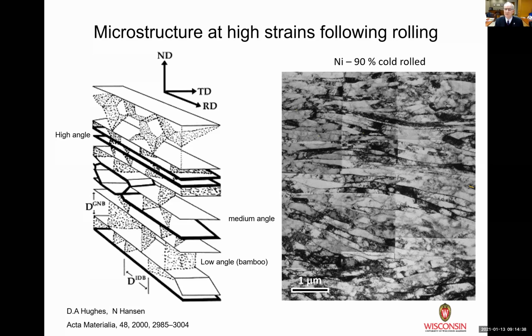Now, if you think of moving a dislocation in this structure, it would be very, very different than the one I showed you at the beginning in the little movie, right? The microstructure is more complicated. There are more barriers to the dislocation motion. And the more barriers there are, the more stress, more load you're going to have to apply in order to get the dislocations to move. So this is what happens just in a metal, no hydrogen, just loading up the material.